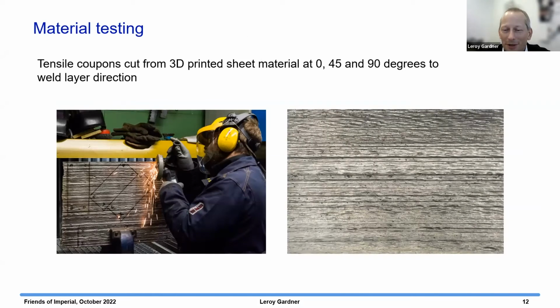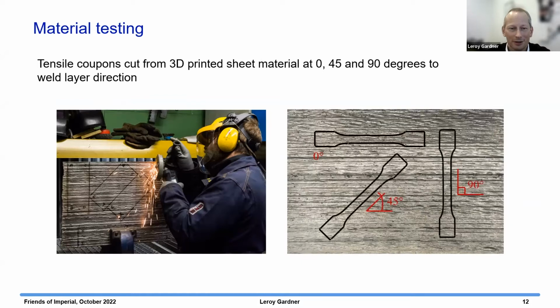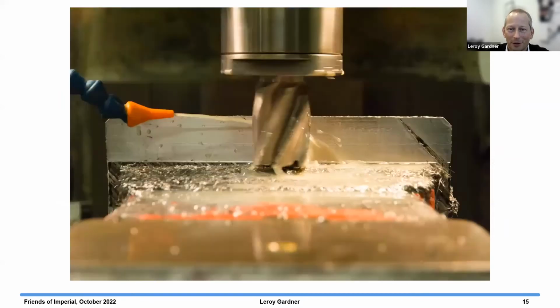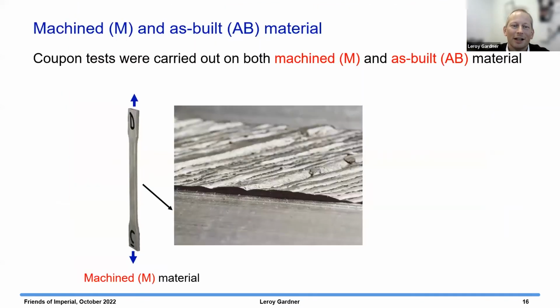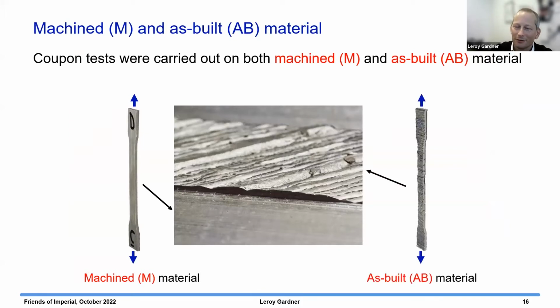Now, this is a layered material, and so we thought there's likely to be an influence of direction of testing. So we cut out coupons at different angles to the print layer direction. We also thought that the surface finish would have an influence on the behavior, so we milled down some of the coupons to get them flat. We conducted separate tests, some on machined material to get the underlying material characteristics, and some where the surface roughness was left in place to get the as-built characteristics. The bridge was not machined in any way after it was printed, so the actual bridge was left in the as-built state.